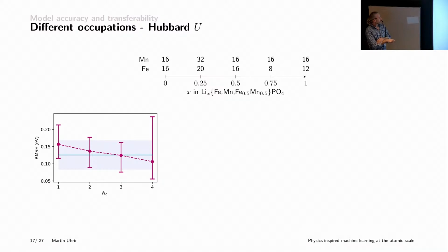And the results I get are like this. So if I only show it 1, it's not doing as well. And when I say as well, I'm using the blue line as a reference, which is when I show 80% of all of these and predict on the remaining 20. But then by the time I've shown it 2 out of the 5 of these, it's already doing a very, very good job.